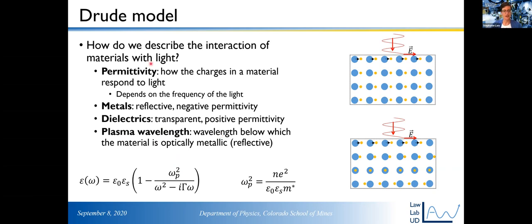And in the Drude model, the plasma wavelength, or the plasma frequency, depends on the density of free carriers, electrons in the case of all of our materials. Again, these are just some constants, and then the effective mass of the carriers, right? So by changing the density of electrons in your material, you can change its plasma wavelength. You can change the wavelength at which it goes from being reflective to being transparent.